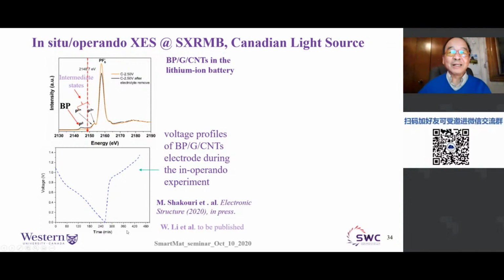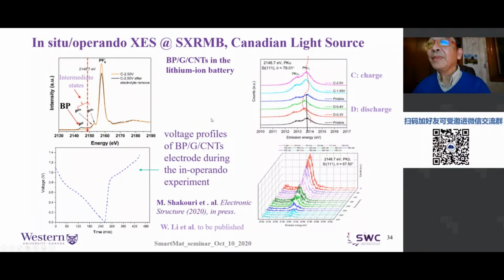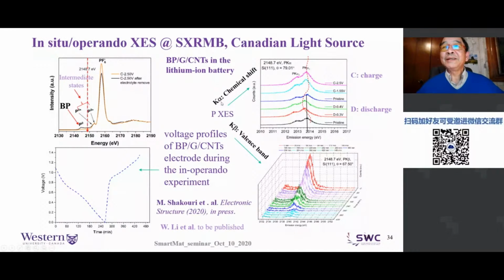So here is just a curve that describes how the cycling is done. By exciting this energy, we don't have to worry about fluorescence coming out from the electrolyte and the intermediate states, because we don't have enough energy to excite them. Okay? So here are the spectra, how it changes. C here stands for charging, D stands for discharging, and the pristine, of course, there's no charge. And you can clearly see the cycling is taking place. Now, this is a very quick experiment just to demonstrate the capability, okay? And this is the K beta. So as I mentioned earlier, K alpha gives you the chemical shift, and K beta gives you the valence band, right? Okay, and the science is still being written up, and we have a lot more detail about these things.